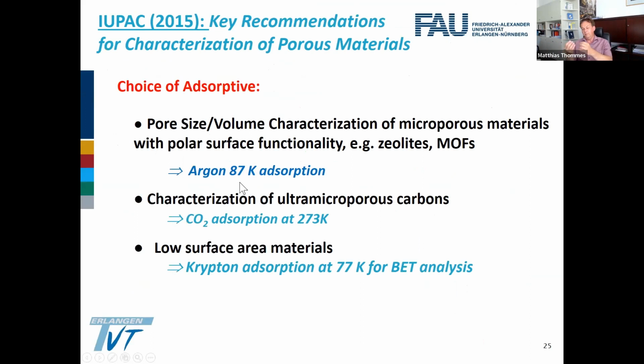If we have a problem with nitrogen, that it interacts due to quadrupole moments with polar surface functionality, of course, it has been shown that this has a huge effect on the pressure or chemical potential at which pore filling happens in materials such as zeolites or metal organic frameworks, which all have polar surface functionality. And also here, argon at 87 Kelvin is therefore the suggested adsorptive. This is a suggested probe atom to go for.